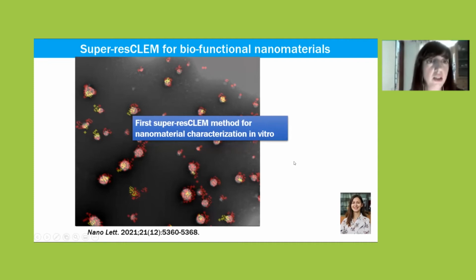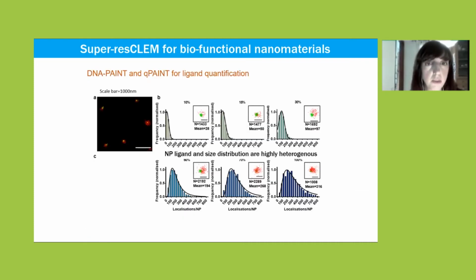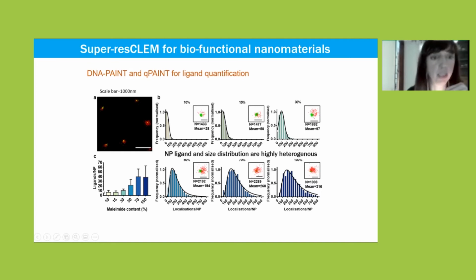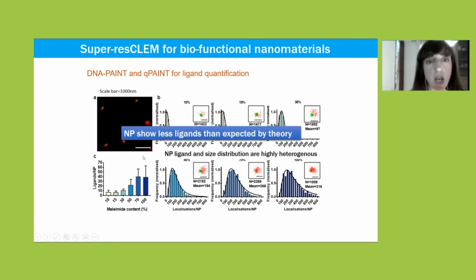And it's not only beautiful images, as you can see here, but we can get a lot of data out of it. For instance, we can learn, as I was telling you, about the number of ligands that we have on the surface of the nanoparticle. So we can make different formulations with fewer or more ligands on the surface and learn, by counting and applying Q-paint, the number of ligands that we have on them. Okay, and this was surprisingly low. It's much less than what is expected in theory.